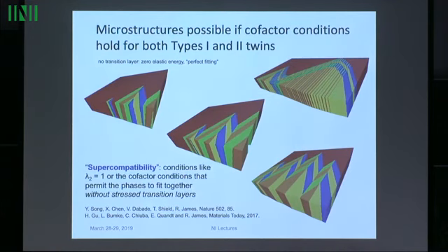And in hindsight, we realized, and this concerns a whole slew of open questions, that we began to get the idea that it's really the complete removal of the elastic transition layers that may be the most important aspect of compatibility.